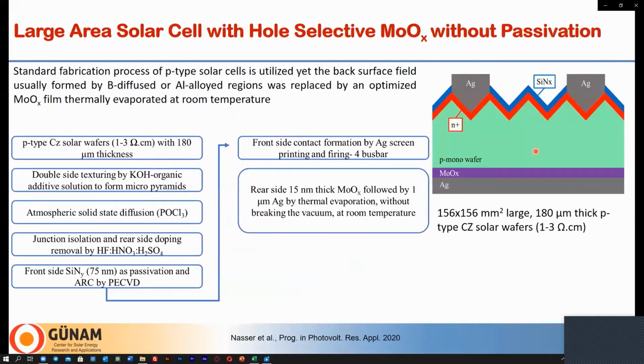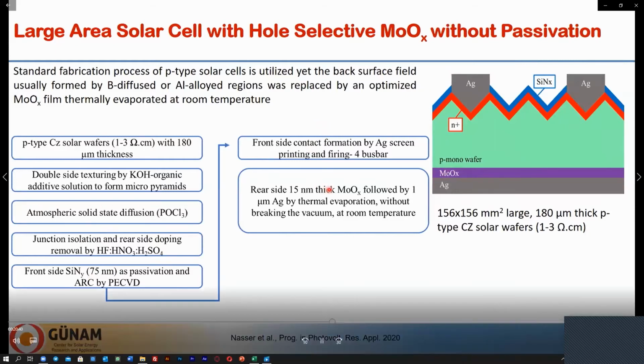So with this motivation, we have applied molybdenum oxide in the fabrication sequence of an industrial scale solar cell on P-type monocrystalline silicon wafer. This is the solar cell fabrication, and we have applied molybdenum oxide at the back side here. We used M2 Czochralski grown wafers, and we followed this procedure. First, the cell was textured, followed by diffusion on both sides. Then the back side was isolated, etched, removing the back doping. Then we applied silicon nitride on the front side, which acts as passivation and anti-reflection coating. Then we made the four-busbar screen printing and firing, and the back side was cleaned again, and then we applied molybdenum oxide, followed by silver. And this is the obtained cell.